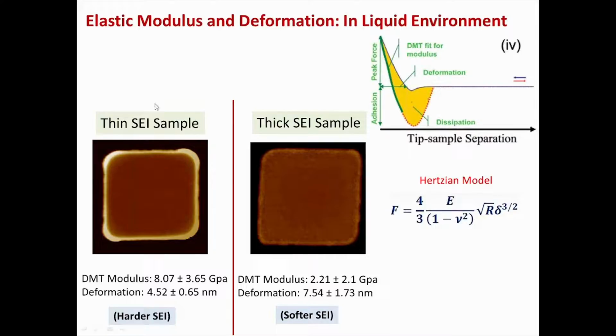That's what we did here, and what you can see is that the thin SEI sample is formed at lower potentials, and the thick SEI sample is when it was held at higher potentials, like 0.6 volt. There is a clear difference in the kind of elastic modulus you can measure. Clearly, the very stiff SEI is not going to work very well because it will be more brittle compared to the softer one. All these measurements were done inside liquid, so they are reported from the liquid environment.